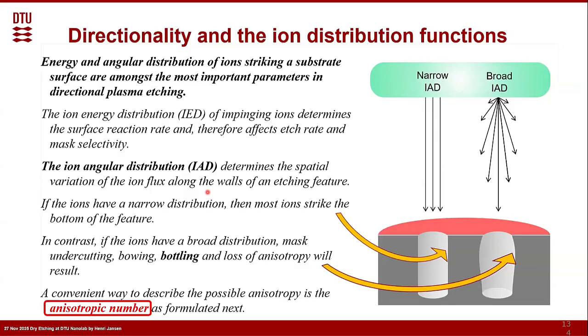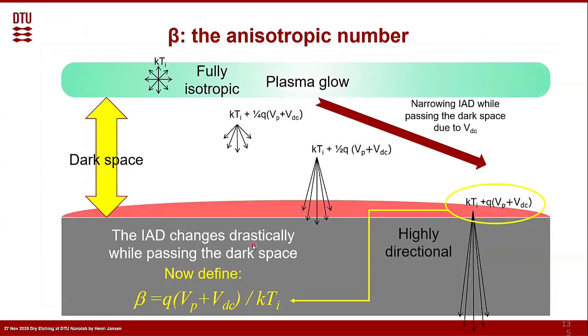determines the spatial variation of the ion flux along the walls of the etching feature. If ions have a very narrow distribution, like here, then most of the ions strike the feature at the bottom. And in contrast, if the ions have a broad distribution, like here, you will see that ions also will hit, maybe with sufficient energy, the sidewall and knock away the passivation layer over there. That results in undercutting, bowing, bottling, and a loss of anisotropy. Now, a convenient way to describe the possible anisotropy is what we call the anisotropy number. And we will talk about it now.